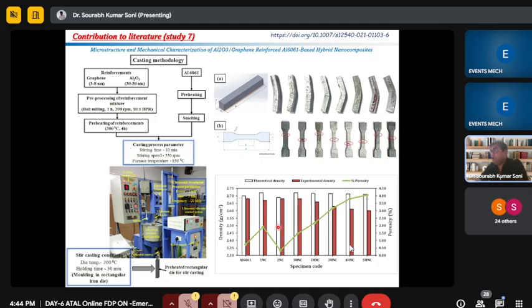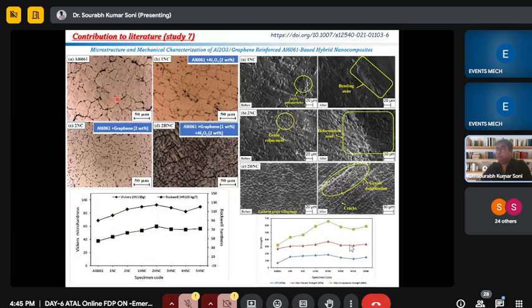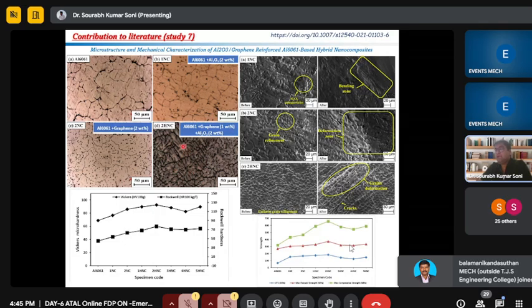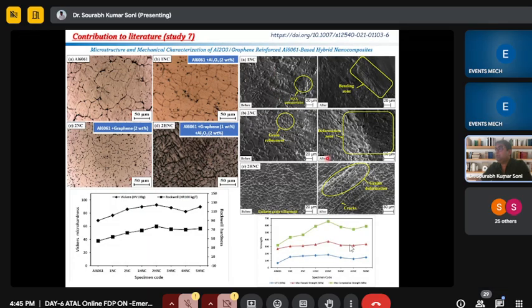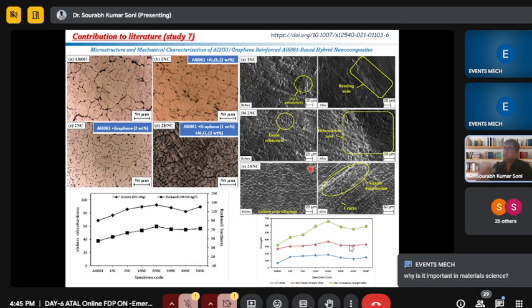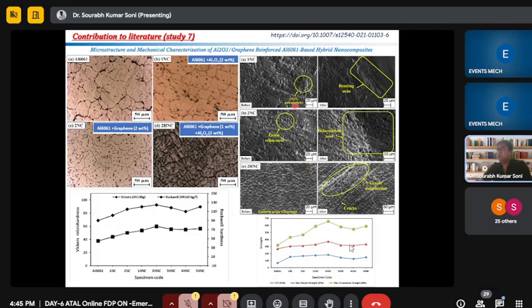What is the trend that is going on? If we use different percentages of reinforcement and different processing technology, we can analyze it with the density of the specimen. Then here, optical microscopy. Here I have observed that the graphene and Al2O3 hybrid composite specimen has very high grain refinement. So it has some implication in the mechanical property also. This is the same image showing the flexural strength: why it has very low flexural strength, why it has very high flexural strength. We can relate it with this kind of property-structure relationship.